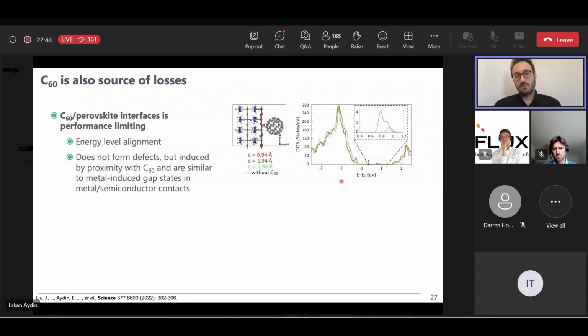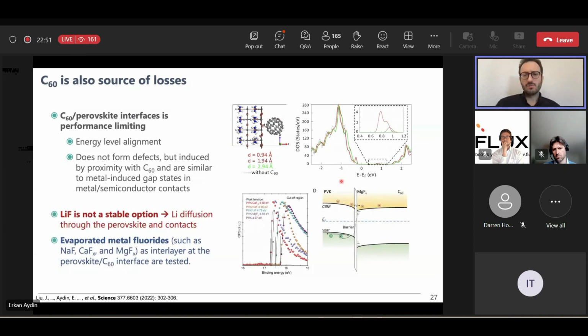And actually, we were working with the calculation team, and then we understood that if we approach the fullerene layers towards the surface of the perovskite, we start to form a kind of defect states within the band gap, but this is not a defect state from the fullerene itself. These are actually induced defects, which is a very well known thing in silicon research as well, metal-induced gap states, and basically the wave functions of the perovskite and C60 are overlapping and it's behaving like a defect. So the only way to solve that is displacing the contact between perovskite and fullerene, and this was done